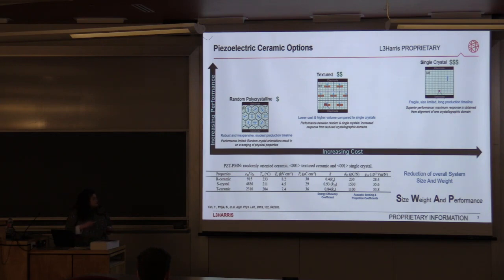And what I've shown down here is just some properties where you can see this k here is kind of your energy efficiency coefficient. So single crystal is going to be approaching 1, and then here would be polycrystalline, and then just here is an example of textured, where we're actually approaching this really high efficiency coefficient. And what this means for us in transducer design is a reduction of your overall system size and weight using something that's textured. And we like to refer to that as SWAP, which is size, weight, and performance. And we talk about that kind of all the time.